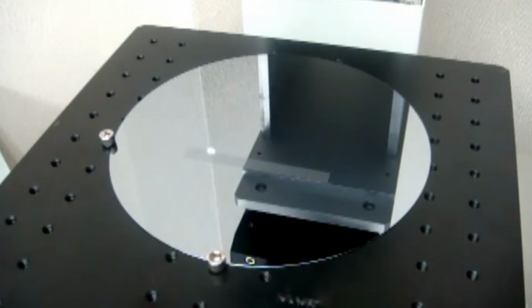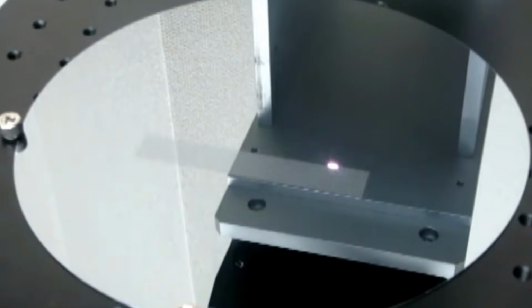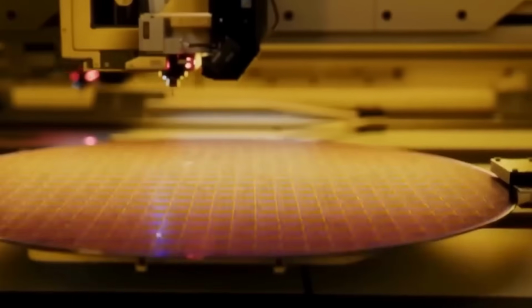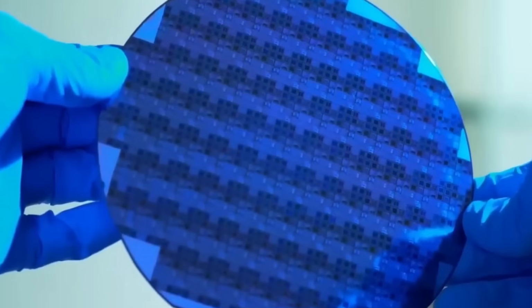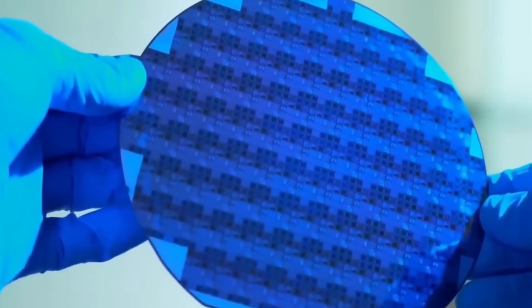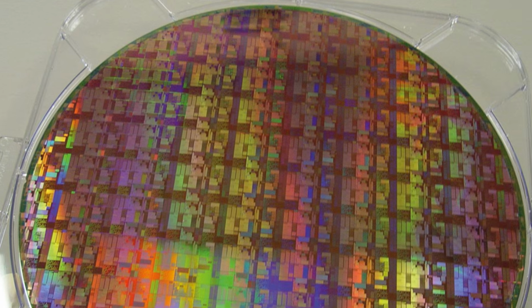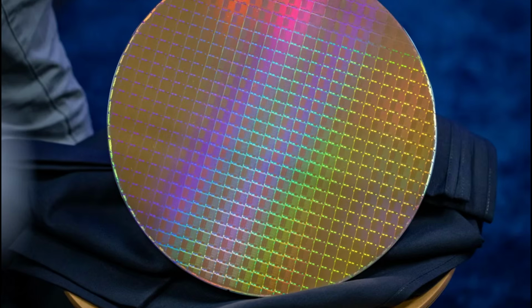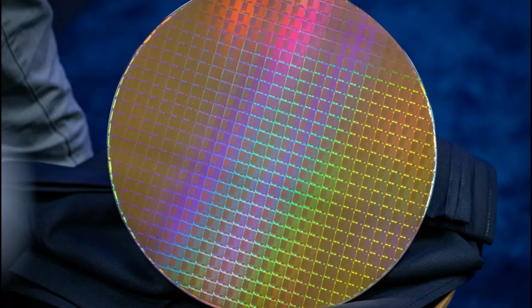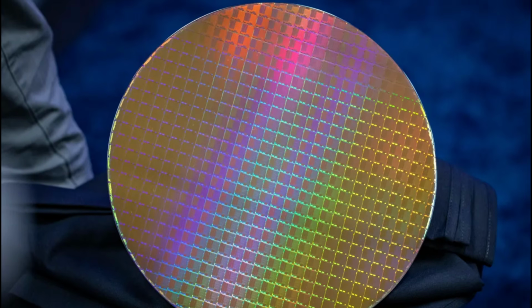Laser scanning systems sweep across the surface, detecting particles and crystal defects far too small for any microscope operated by human eyes. Flatness is verified in nanometers. Electrical properties are measured point by point across the entire disk. If the crystal structure shows dislocations, if the surface shows contamination, if the resistivity drifts outside specification, the wafer is rejected. Because a defect at this stage doesn't cause one failure. It multiplies. A single wafer can hold hundreds of individual chips, and every flaw silently kills the devices built on top of it, sometimes without being detected until months later.